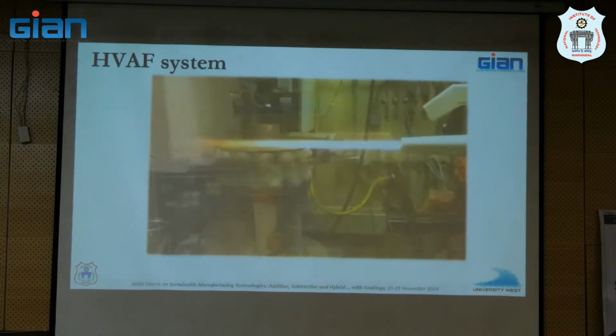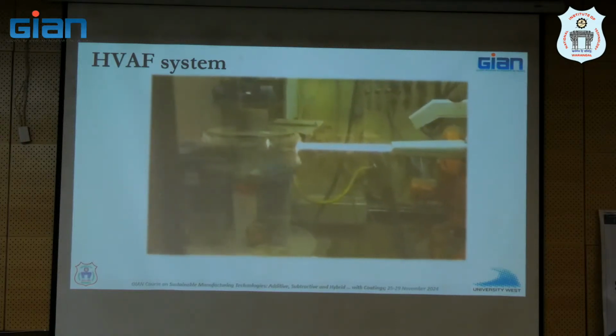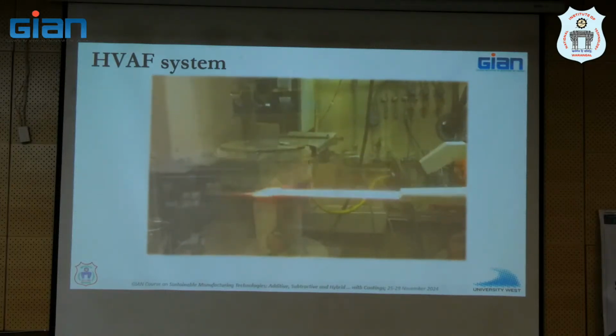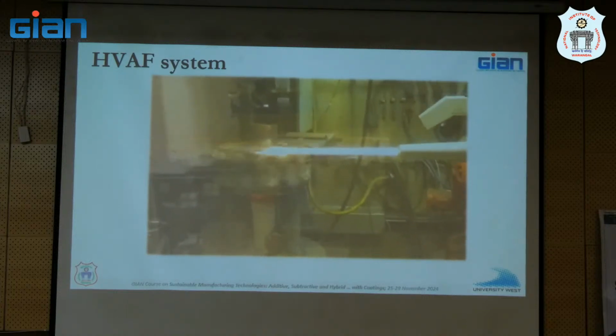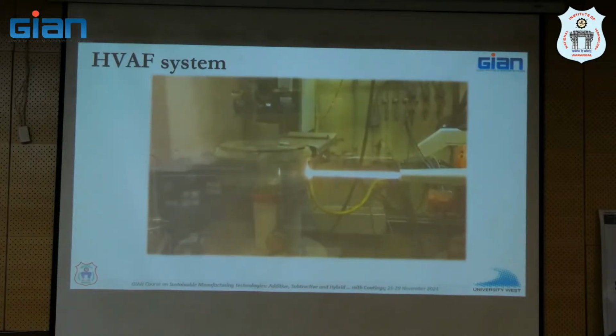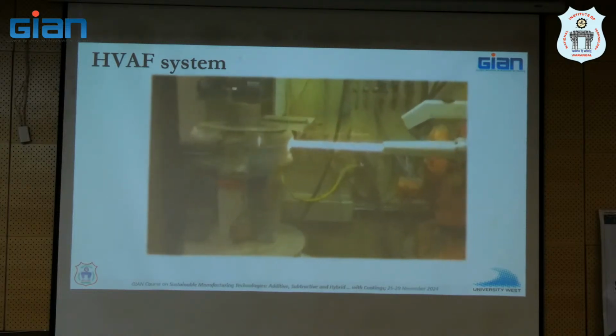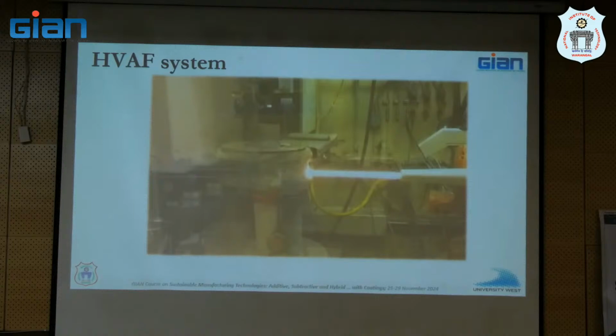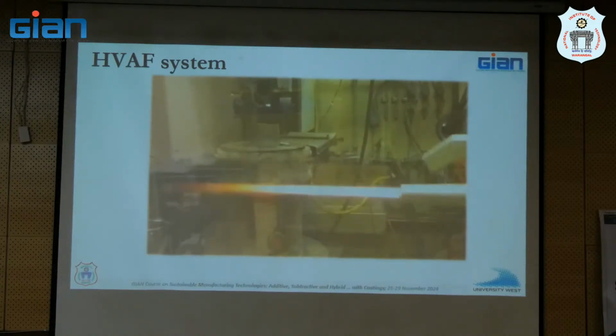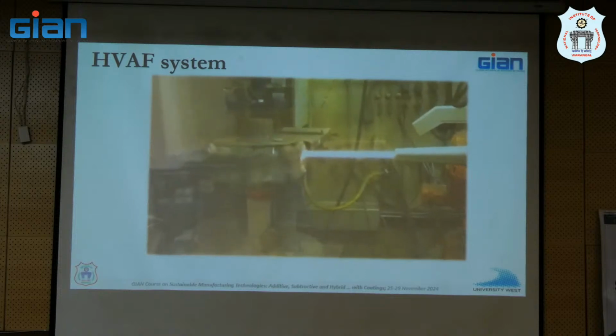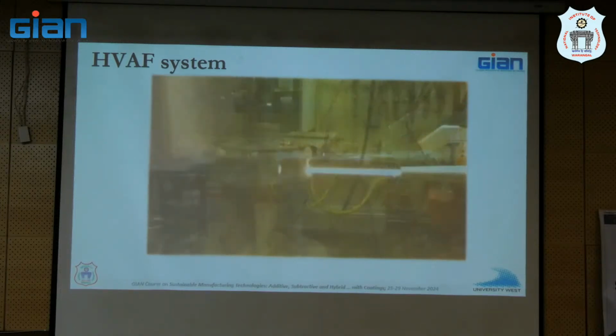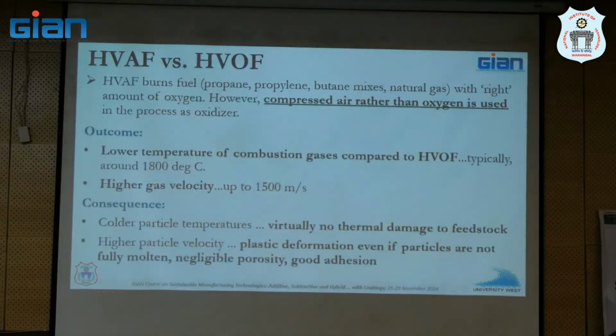Yeah. This is a high velocity air fuel system from my lab. Looks very nice, doesn't it? Very stable flame. We use this mostly to spray tungsten carbide, and this will give you an idea of how high the productivity is. Beautiful flame. We put on almost 10 to 20 microns per pass. Every time that goes around, you build 20 microns, so it's pretty quick. In about 10 rotations, you build 200 microns on whatever part.